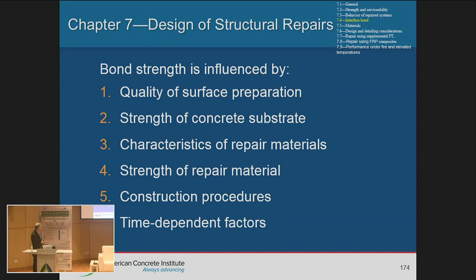So the bond strength is influenced by the quality of surface preparation, the strength of the concrete substrate, the characteristics of the repair material, strength of the repair material, construction procedures, and time-dependent factors. And what do I mean by time-dependent factors? For example, if you want to have an overlay, and you apply epoxy on the substrate, and you leave it for a couple hours, and then come back to put your overlay, what will happen with that epoxy? It will solidify. It will lose its stickiness or its bonding. So when you come with the overlay, will it bond to the existing? It will not. So you'll get that delamination, or it will not bond, so it will not work together. So that's what's meant by the time factor.